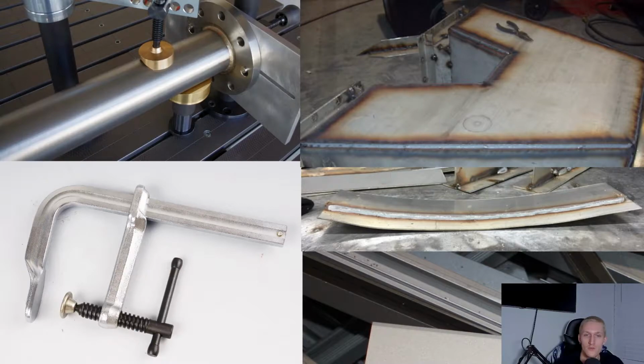You can also use GMAW-P, which is sort of like spray transfer because the power source switches between peak current and background current from 30 to 400 times per second. This allows a droplet to be pinched off when the switch happens to the peak current. This allows the pool to freeze slightly and prevent burn through with a clean arc and minimal spatter.